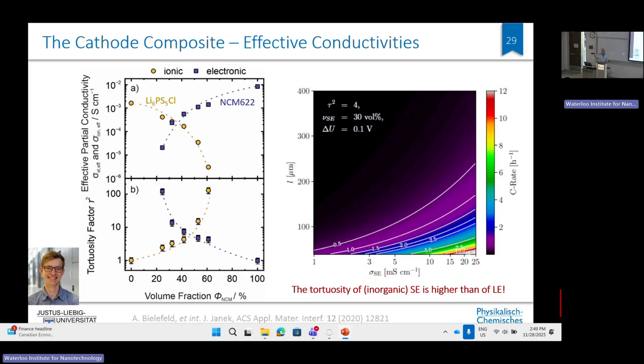That's why, of course, cathode particles are small, to have a short diffusion length for the incorporation and excorporation of the lithium. There's a sweet spot here somewhere, I would say, in the middle. And what Anja did, she calculated in principle what the conductivity of the electrolyte should be to have a good path for the ions. And that is where the 10 millisiemens per centimeter came from, from simulation. We simulated that 10 millisiemens per centimeter are needed at least to have efficient enough ionic transport across that.